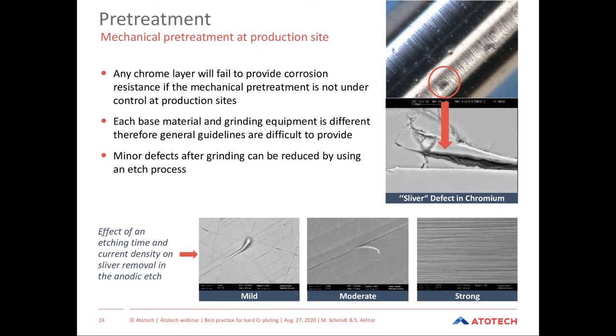By adjusting the etching parameters, they can be etched away. You see on the bottom side with a mild etching on the left side, the sliver on the surface would stand up due to the current which is applied. By increasing the etching, in the middle picture, the sliver is standing up further, and with the right and strong enough etching parameters, the sliver will be etched away.